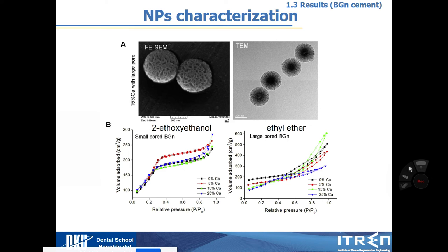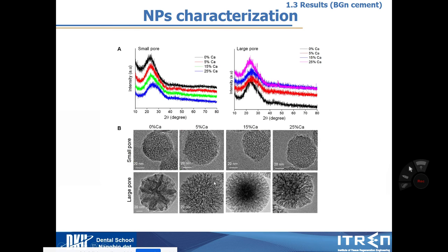So for making this kind of BGn cement, I controlled their calcium composition and their morphology. So I can make small pores like this and large pores like this, and then different calcium composition from 0 to 25%. And then I checked their bioactivity using XRD, which shows an amorphous pattern, which means glass, the typical type of bioactive glass, in small and large pore and with or without calcium.